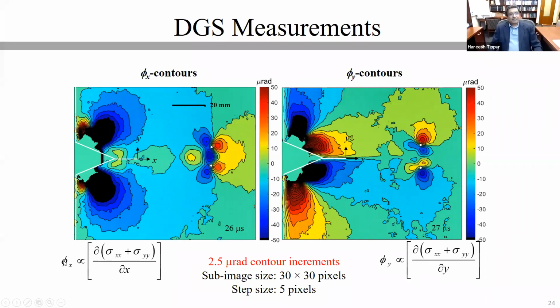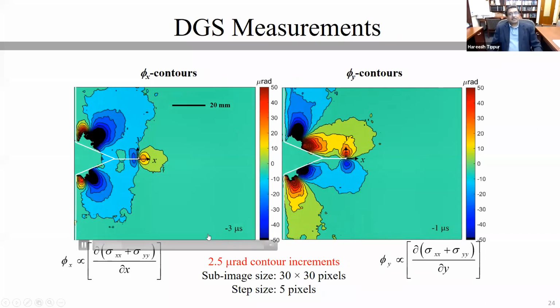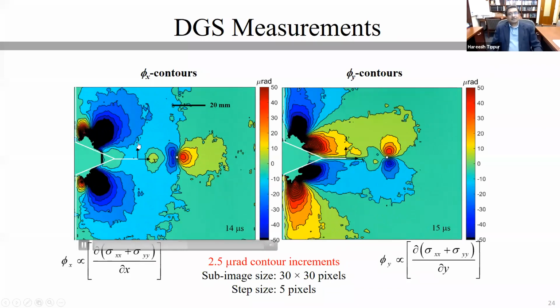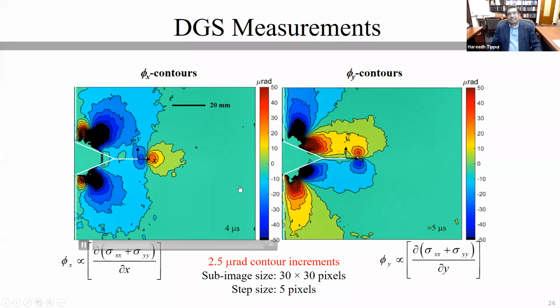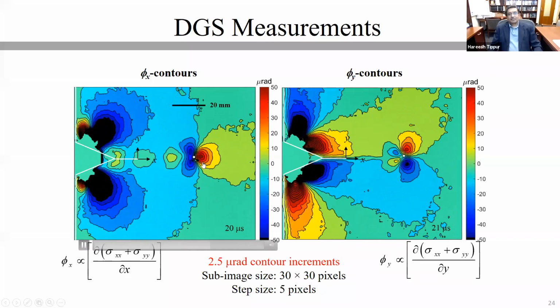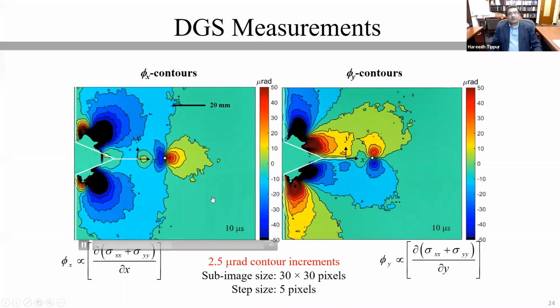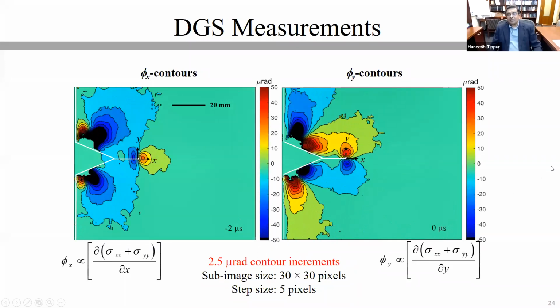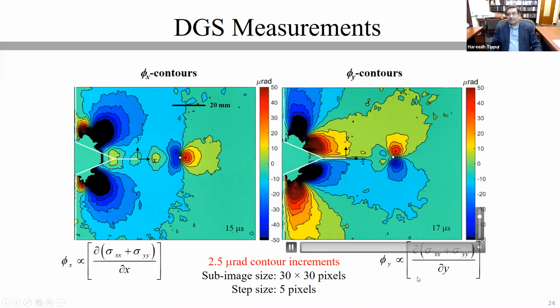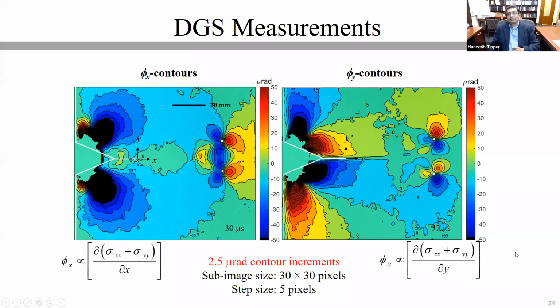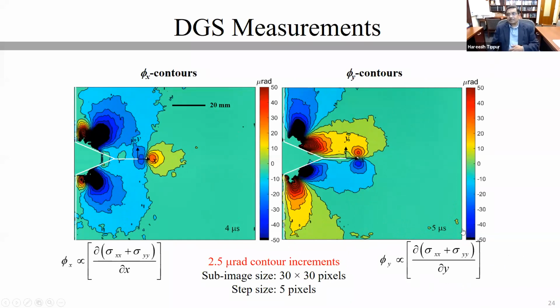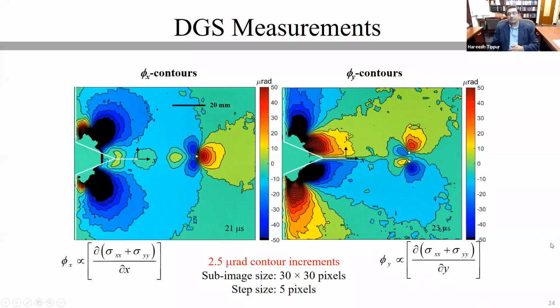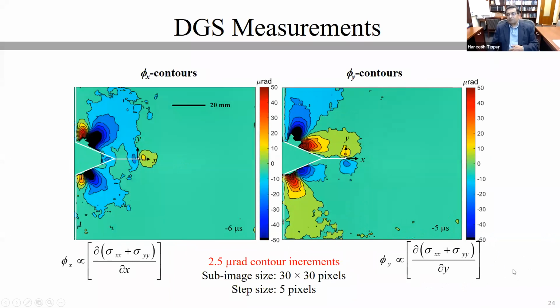Here, the left-hand animation tells you the evolution of the phi-x contours from the original crack tip, which propagates for some distance and then branches out into 2 crack tips. The crack tips themselves can be tracked by looking at those white dots that we have placed artificially on the contour pattern. On the right-hand side, you see the contour patterns in the other direction. The gradients are in the direction normal to the crack path itself.